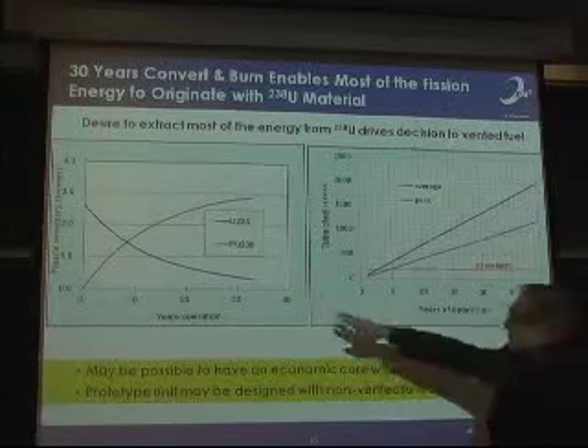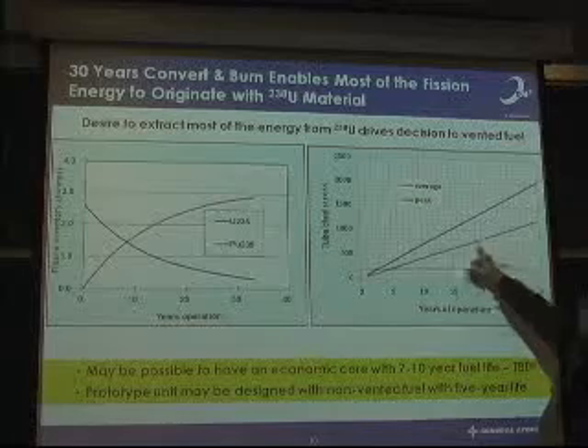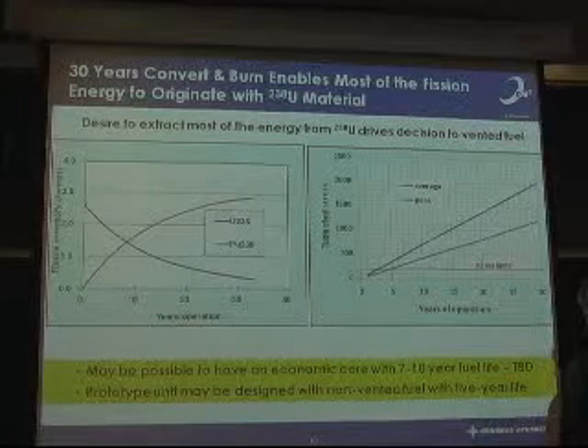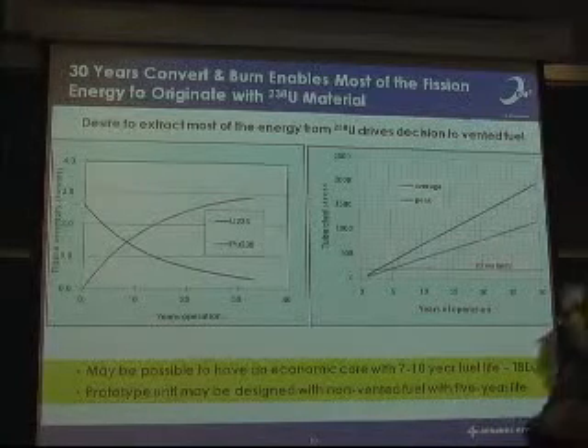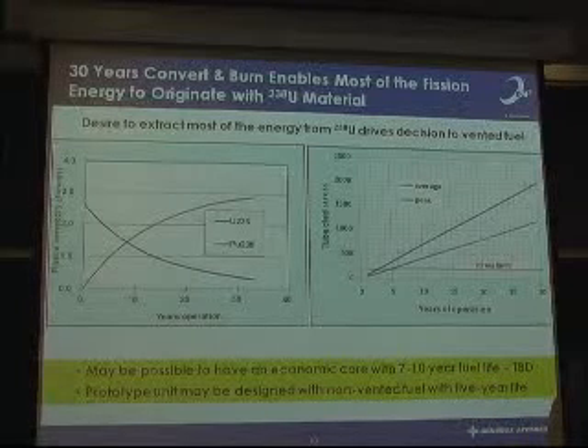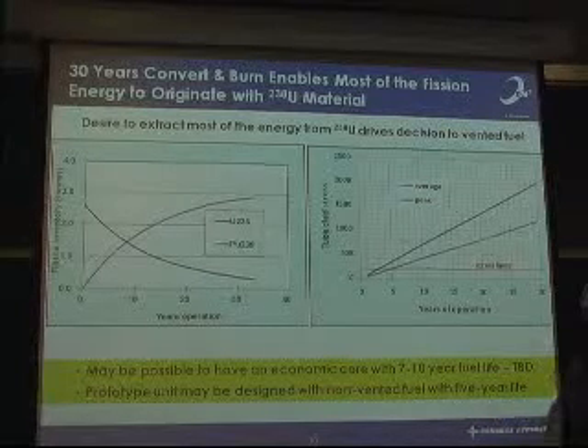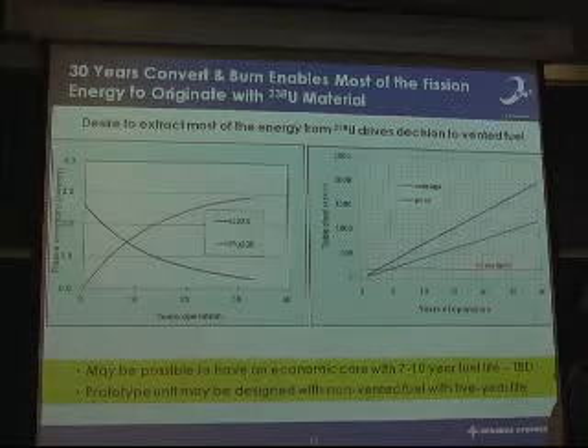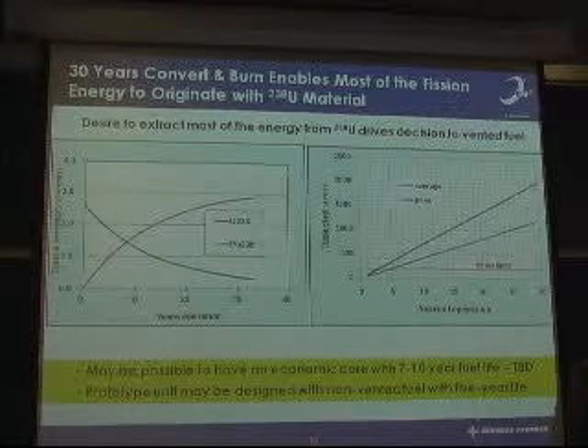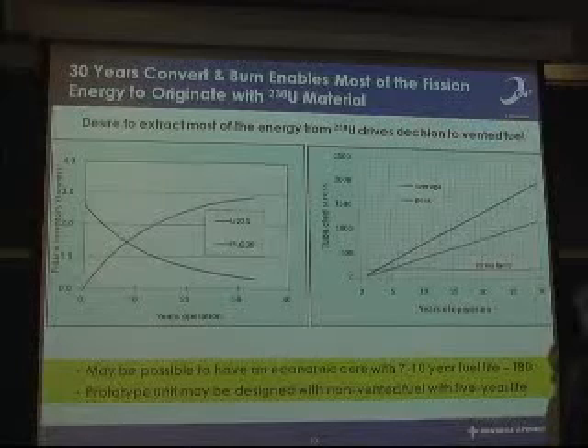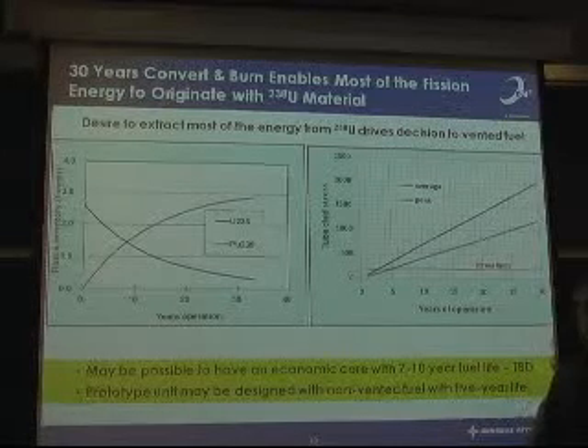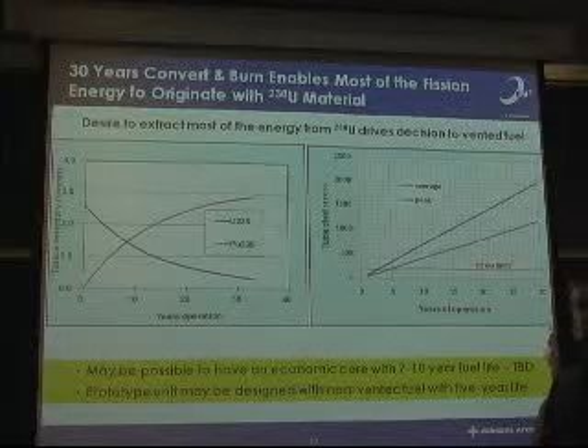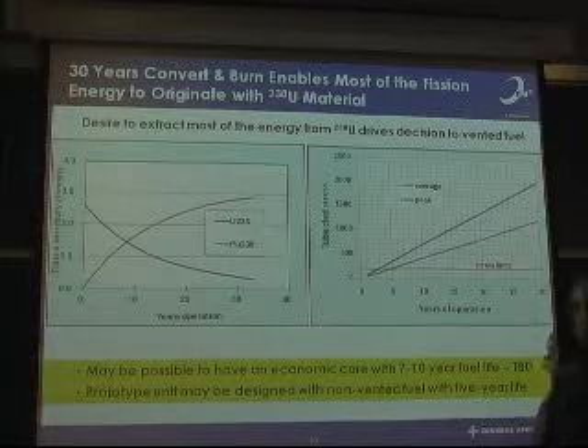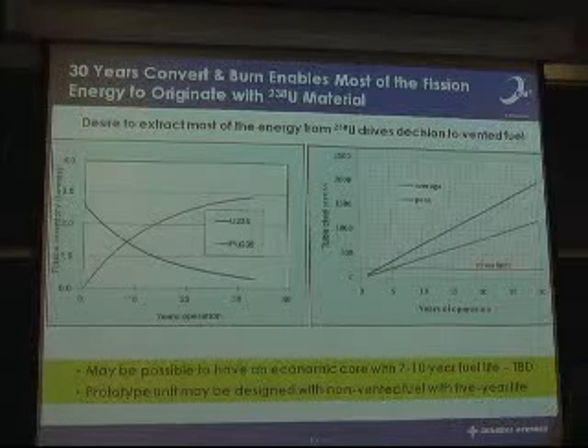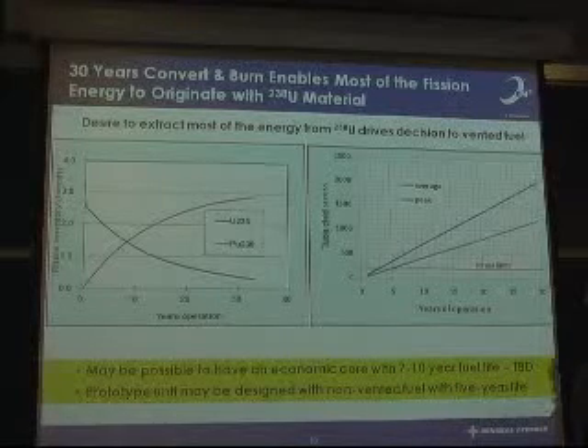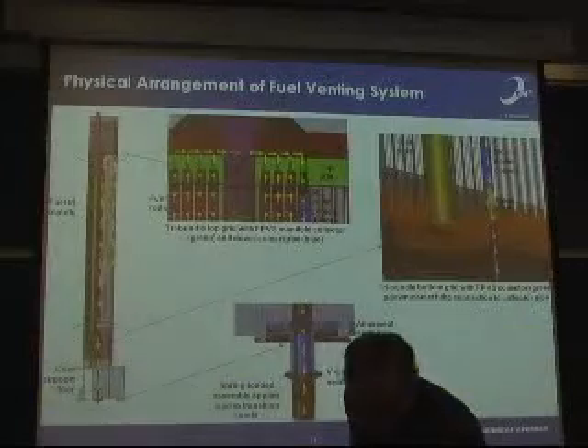But when you have a 30-year core, you build up a lot of pressure inside the rods from the fission gases. And if you decided that you want to make a rod to contain that pressure, you just couldn't do it. You have to vent the fuel. And so right off the bat, we had to make a decision to vent the fuel. Now, lots of reactors have been built with vented fuels. The British Magnox and AGRs were all vented. Our first reactor at General Atomics, the Peach Bottom reactor, was a vented fuel design. Worked fine. We think we know how to do it. And so we decided to vent the fuel.